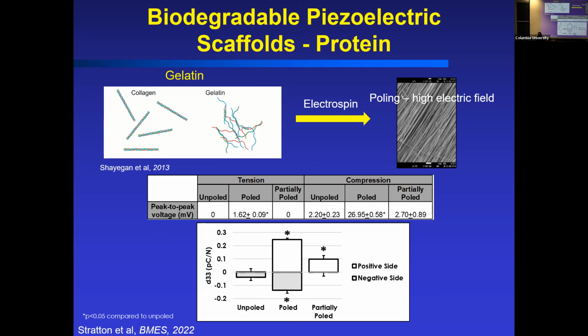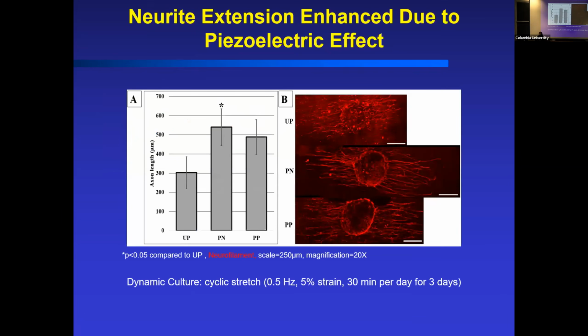And again, for these injuries, ideally, we would want the material to go away or degrade. So we're going back to this gelatin, this protein-derived piezoelectric material that biodegrades. And again, we can alter the level of poling on this to achieve higher piezoelectric output in those materials. And so our recent work shows here, and my student Scott Stratton is presenting this at BMES, that we are getting enhancement of neurite extension on those poled materials. And this is in a stretch device. So we're actually applying a cyclic stretch to those DRG neurons, 30 minutes every day for about 3 days.